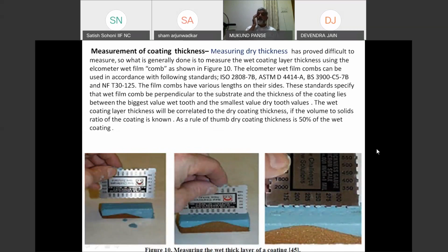For checking thickness of the paint, when you have done all this, how to check the thickness, whether it has been correctly applied. There is a standard gauge for all this. It is difficult to check the paint thickness after it is dried. So wet paint is checked with this. There are depth markings on this at various levels, and to what depth paint is there, that is measured and standardized for your application. There is an ASTM standard for this application. Normally, as a thumb rule, the dry coating thickness is half the wet coat.